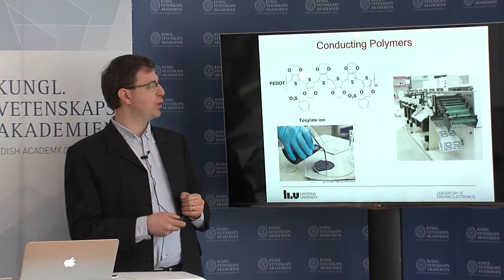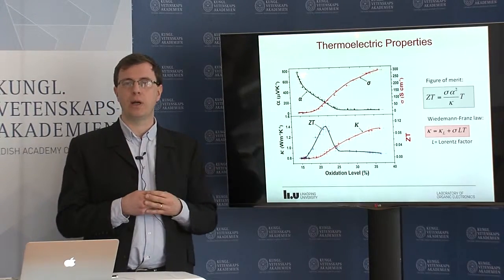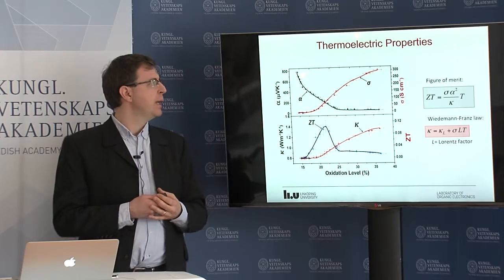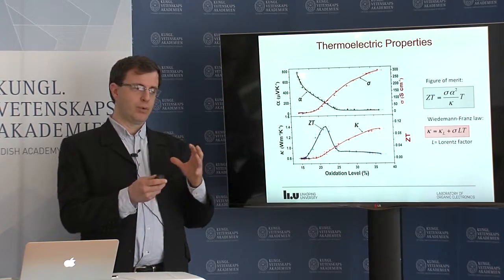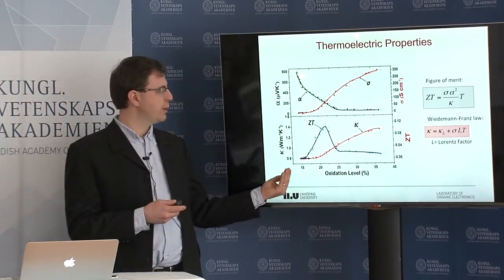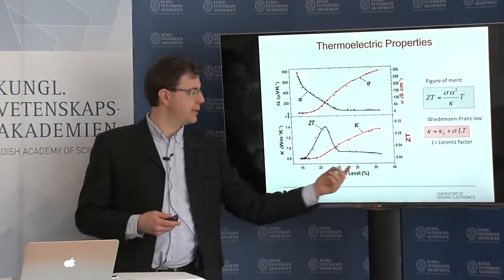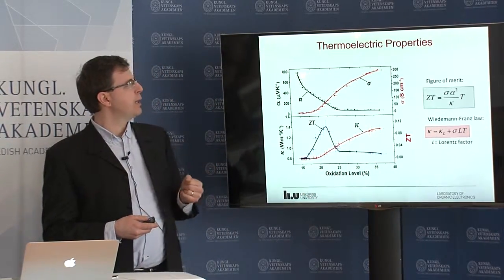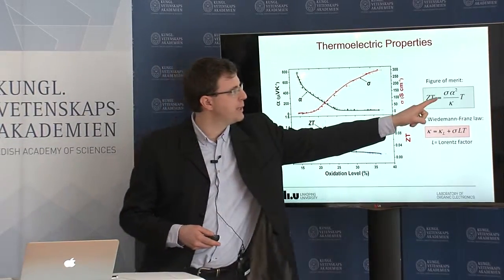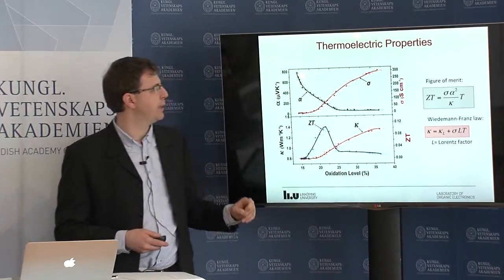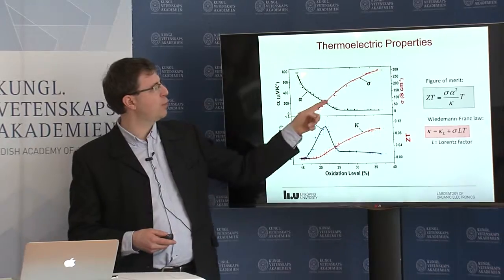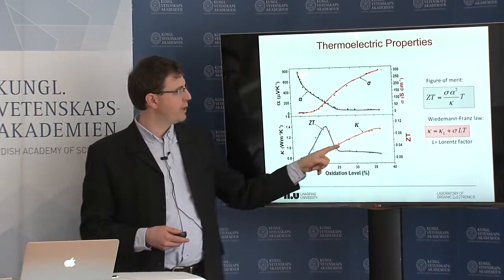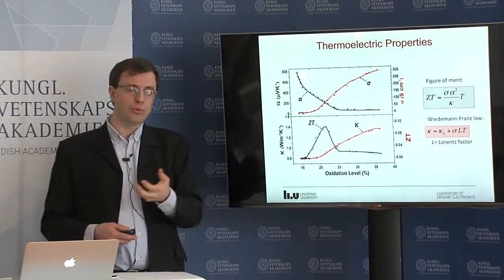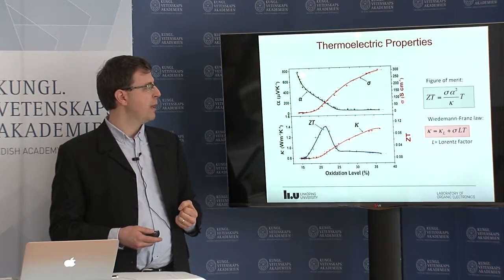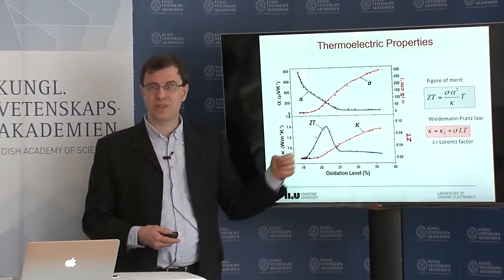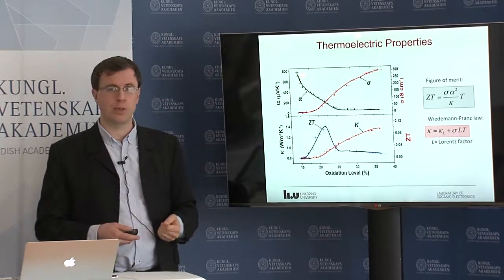So this is what we have done, basically. We have studied and optimized the thermoelectric properties of these kinds of conducting polymers. We have found ways to improve that by improving the molecular order and also tuning the doping level or oxidation level. So you can see that as a semiconductor. Here we investigate the three properties: electrical conductivity, Seebeck coefficient, and thermal conductivity. So when you increase the doping level, the electrical conductivity increases. At the same time, the thermal conductivity also increases because part of the thermal conductivity is due to the charge carriers that are carrying heat. However, the value of thermal conductivity is still very low because it's a plastic, it's a thermal insulator.